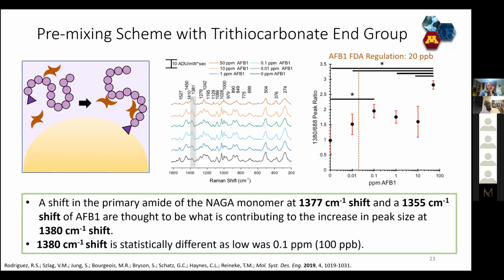And we do see a new band. That band that's highlighted in gray actually seems to be a combination of both some piece of the aflatoxin and the polymer that's there. And when we go through and look at how the intensity changes as a function of the aflatoxin we've included, what we see is that we do better than when we had no polymer. Now we can do 100 parts per billion as our limit of detection. Still not good enough though, right? 20 parts per billion is what we need to get to, or even lower.